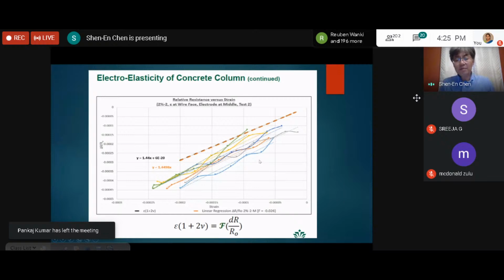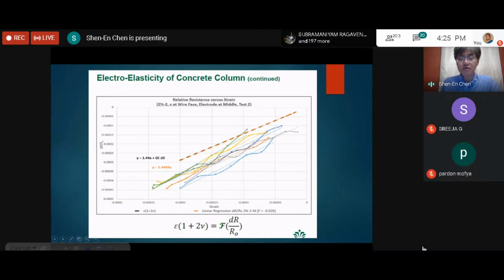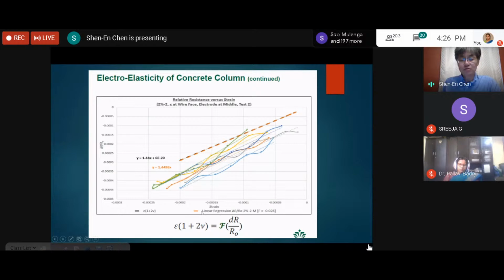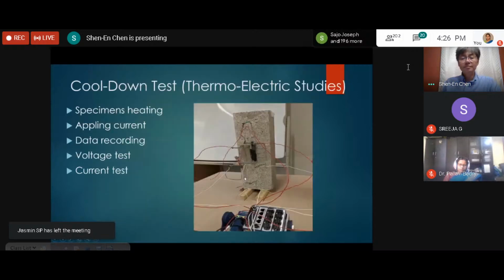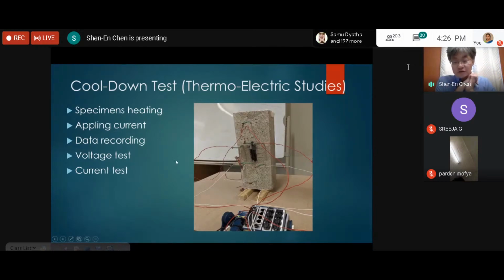Okay, and to make a practical application, you have to use the readings that you developed through the technology. And what you were able to accomplish is that you see there is an assumed linear correlation, so that by matching the linear correlation with the theoretical equation that we have derived, there is an empirical factor F that you have to embed into the measurements, so that you're able to correlate the change in resistance to the change in strain. And then at that juncture, we know that the self-sensing is a very useful technique, and we are actually developing good correlations between stress, strain and also the voltage change in a self-sensing concrete.